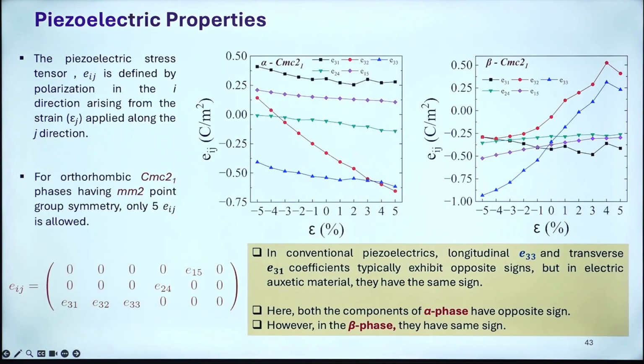Yeah, so then, because we are playing with strain, we also tried to get the piezoelectric stress tensor e_ij. It is defined by the polarization in the i direction arising from the strain coupled with that particular direction. In conventional piezoelectrics, the longitudinal e33 and the transverse e31 coefficients typically exhibit opposite sign, but in electric auxetic material they have the same sign. Here both components in the alpha phase have opposite sign, but in the beta phase they have the same sign. That is what we find, but this still needs experimental confirmation.